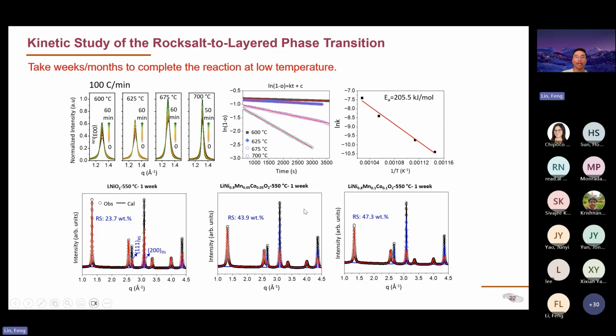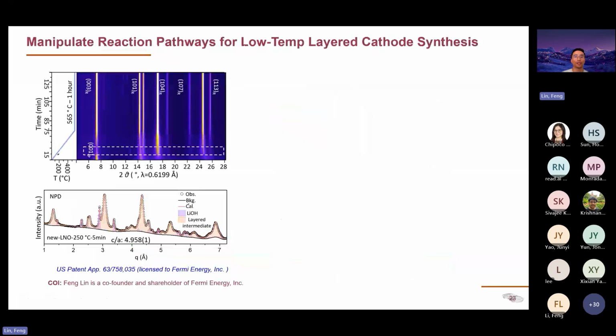and the rock salt percentage increases as we have higher manganese and cobalt. So rock salt still remains at 47%. That means if we use traditional methods, even after 1 week of making at this temperature, we are not able to convert totally to the layered phase. There's still a big fraction that's stuck in the rock salt phase.